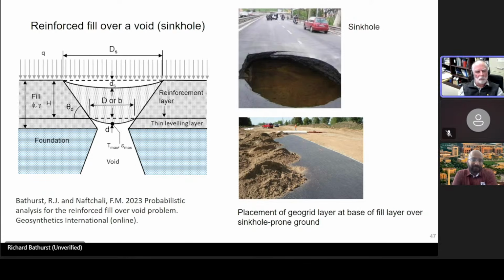Well, what we have done is we've done the calculations using reinforcement stiffness for different assumed durations of time. So, for example, we've taken 1,000 hours. We're assuming a scenario where this void, this bump in your fill, is going to be there for 1,000 hours before you actually fill the void. If the time is shorter, then all of these stiffness values that I've given you, you can calculate what the stiffness of the material will be for shorter durations.